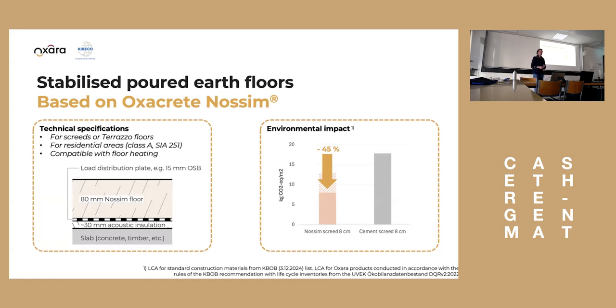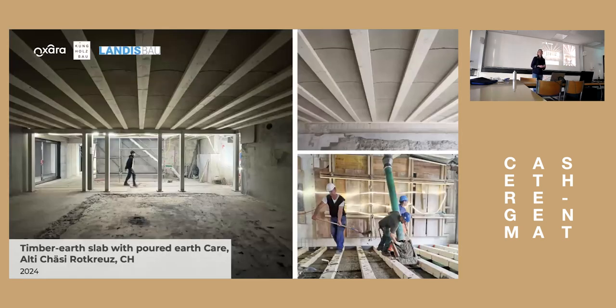And if we compare the Nossim screed of 8 centimeters to a cement screed of 8 centimeters, there's a saving potential of around 45%. But as this is a stabilized floor that we are presenting, it's also not easy to say one number. It again depends on the stabilization dosage that you are using. For the screeds, we recommend 8 centimeters. With other conventional building materials, of course, you can go lower, but as the earthen material does not comply with the norm for screeds, we recommend higher thicknesses so you don't get problems with bending.